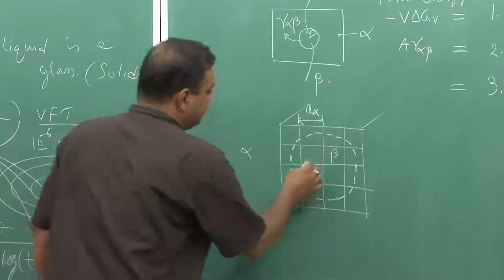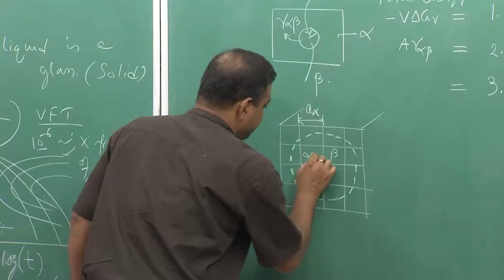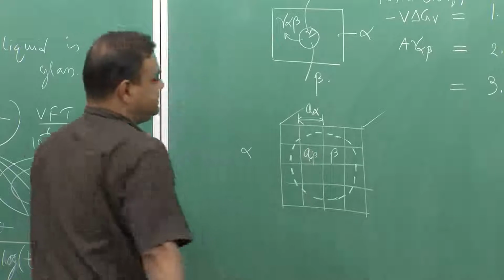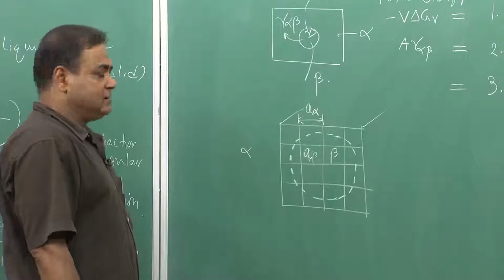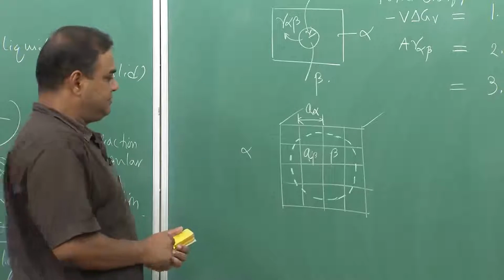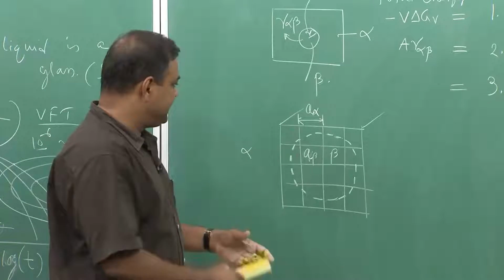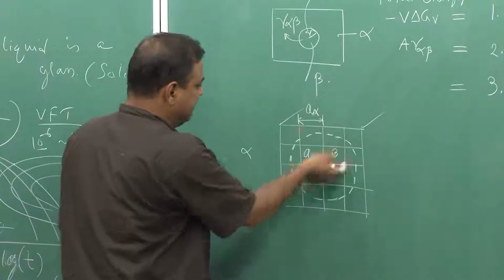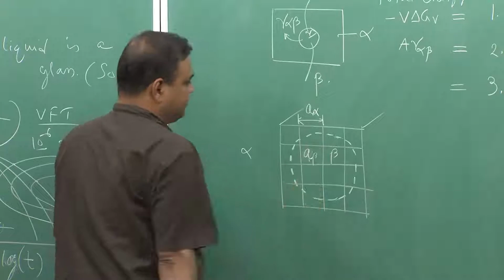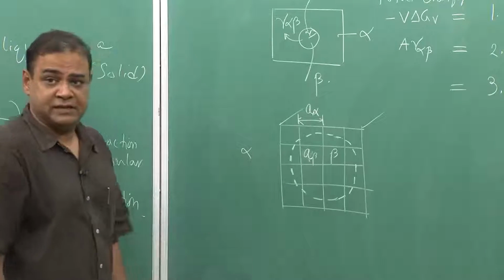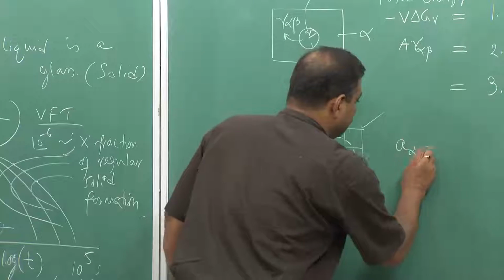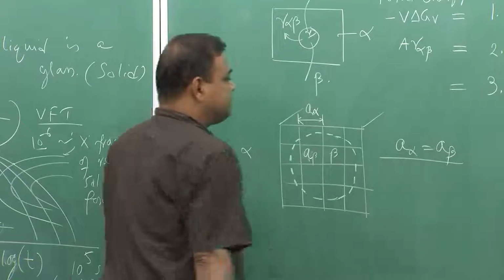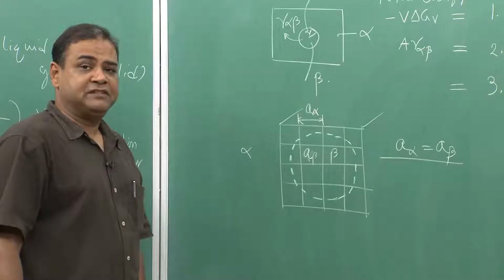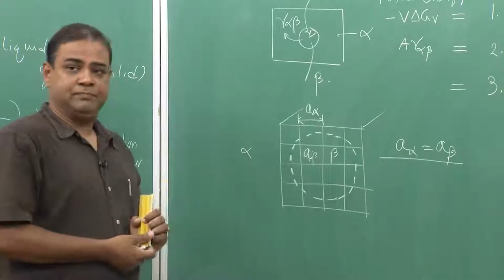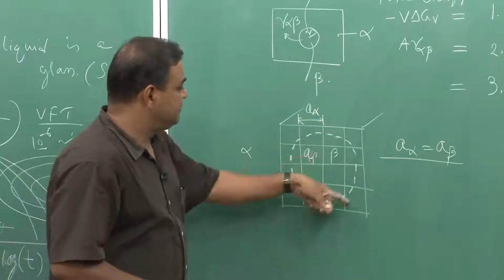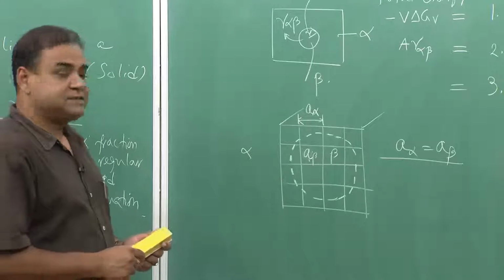Now in case of beta, the lattice parameter is A beta, and from this it is very clear that there is no volume dilation, because before it formed beta everything was alpha, and after formation of beta also this lattice parameter does not change. So A alpha equals A beta. That means the lattice parameter of parent phase as well as product phase are the same, and at that time there is a perfect alignment of those planes. Okay.